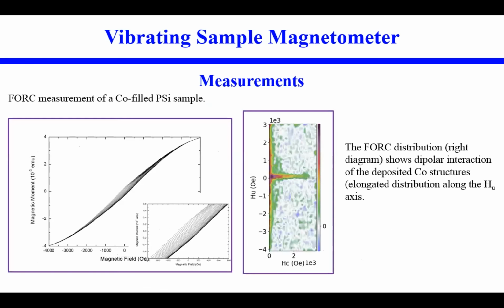And here you see an example of such a FORC measurement of a cobalt-filled porous silicon sample. Here you see the series of FORC curves, and at the right side you see the FORC diagram, which shows the dipolar coupling of the particles inside the pores, which shows this elongated distribution along the Hu axis.